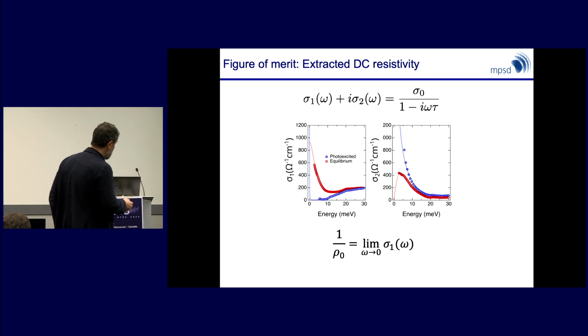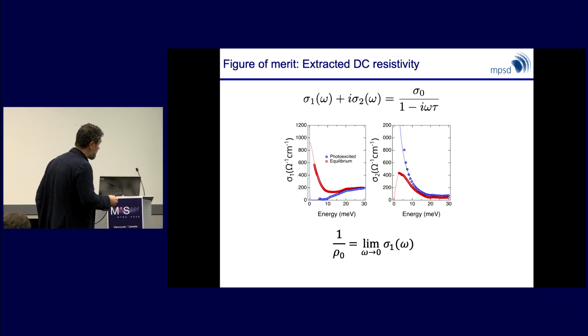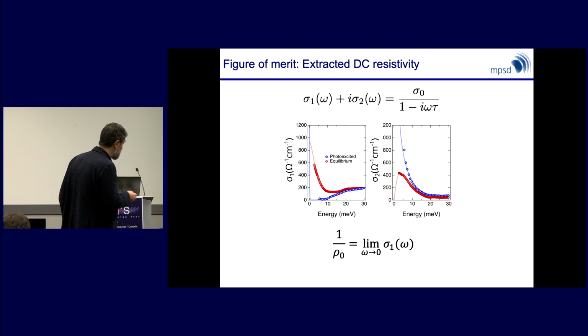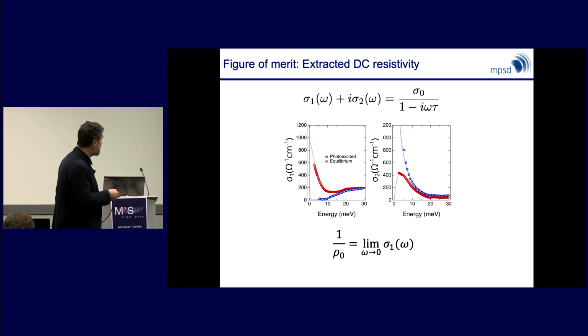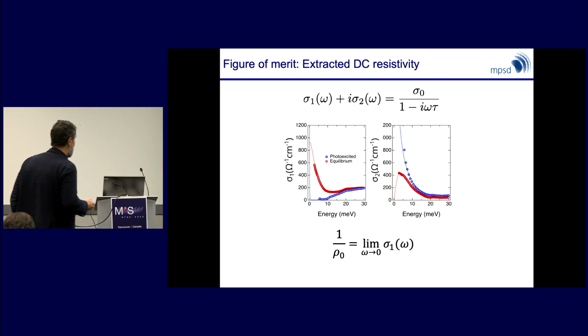So if you do this, you can basically take the limit of sigma 1 for omega that goes to 0 and take this number, sigma 0, which would be infinity in a superconductor, or rho 0, which is the inverse, which would be 0 in a superconductor, and use this to characterize the dynamics.